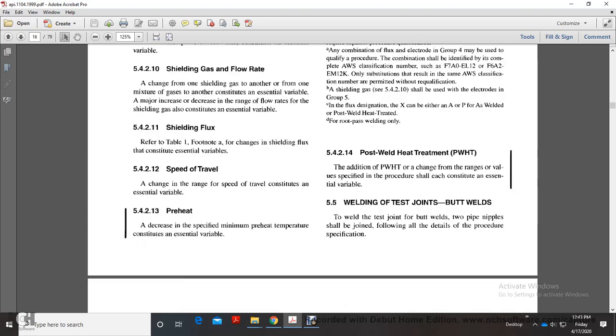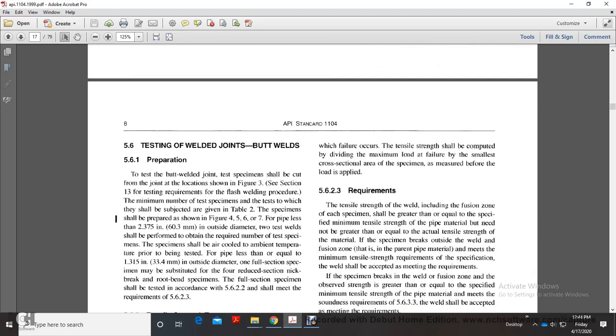5.4.2.14 Post-weld heat treatment, or PWHT. The addition of post-weld heat treatment or a change of the range of values specified in the procedure shall each constitute an essential variable. 5.5 Welding test joints, butt welds. To weld the test joint with butt welds, two pipe nipples should be joined, following all the details of the procedure specification.